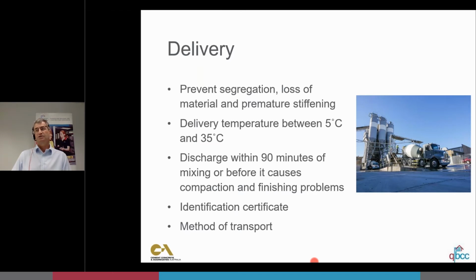Now, when I say that uncontrolled water is a bad thing, I should say that under 1379, you are able to add water as long as the slump is below the required slump tolerance, and it's been no more than 75 minutes since batching, and that you mix it thoroughly after the added water. And I should just say too, if you order 80mm slump, but the placers like it at 120, you're much better off to order it at 120 slump. If we add water to increase the workability, we'll also add cementitious to make sure that all of the strength and durability properties are maintained, which is not what happens when uncontrolled water additions are done on site.